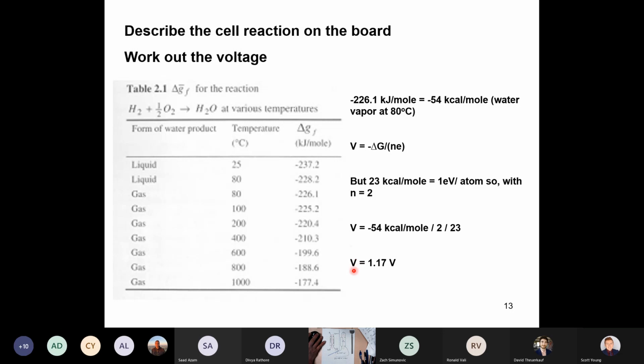And if you think about what happens when water decomposes, well, it splits into hydrogen and oxygen. So it's virtually this reaction running in reverse. And if we had the product being water liquid at room temperature, then this would be very close to the value of the electrochemical stability window of water. So then here they just show what happens to the delta G if the product is liquid at 25 degrees C. You know, delta G is a little bit larger in magnitude than water vapor at 80 degrees C, right? So you get a slightly higher voltage if the product is water at 25 degrees.